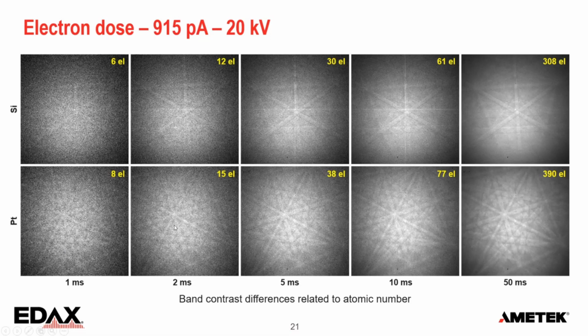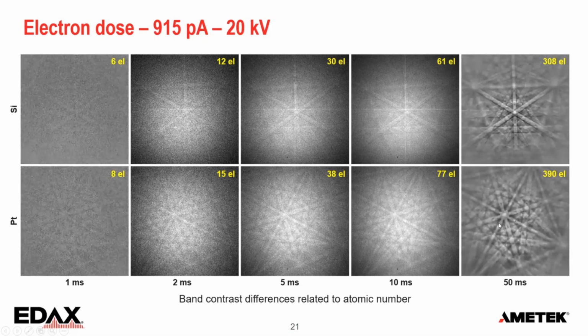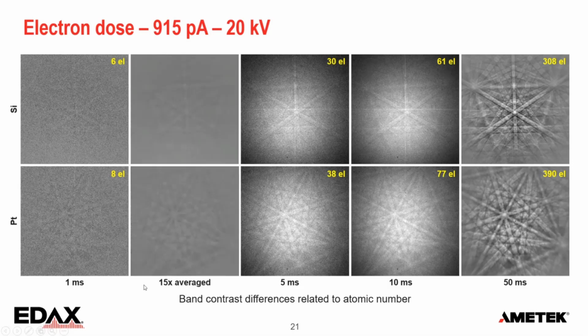And if we go to longer exposure times, you can see the contrast improvement. When we do a background correction at 50 milliseconds, the patterns appear very similar. At 1 millisecond, you can, again, just make out the bands. And if we do some averaging 15 times, we can actually index with these doses quite nicely. So this averaging is something we have to remember. I'll come back to that later.